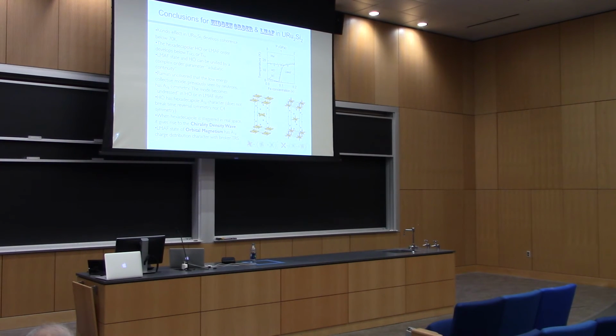Now, Matsuda's experiment, well, technically has not been reproduced, and it is done in the presence of a relatively high magnetic field. So what we know is that when we apply a several Tesla field, that moves the singlets around and does various things. So technically, application of that field is not a perturbative probe. It breaks the symmetry by applying the field. There's still a question why this application of field along X and Y is different. But again, in the high order, it can couple, and that would be okay. But I don't think there's evidence for spontaneous broken C4 symmetry.